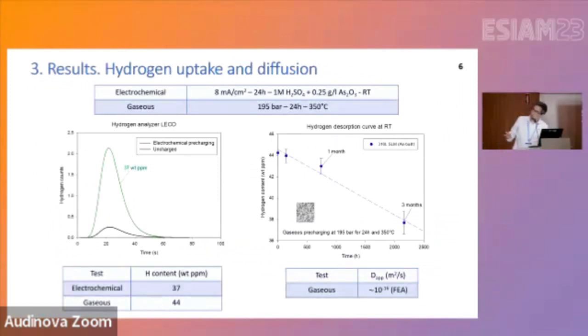Based on hydrogen uptake and diffusion, 37 ppm were introduced after the electrochemical precharging, while 44 ppm were introduced after gaseous precharging. Some of the samples were exposed to air at room temperature in order to evaluate hydrogen diffusion, and by means of this curve, we can obtain the apparent diffusion coefficient, which corresponds to the additively manufactured 316L in this order of magnitude, 10 to the minus 16 square meters per second.